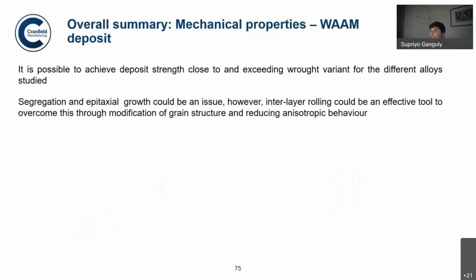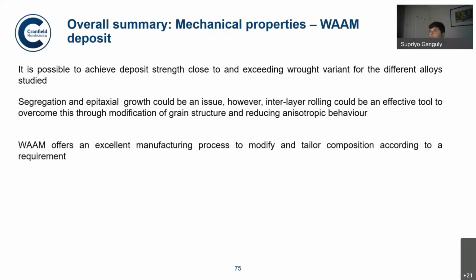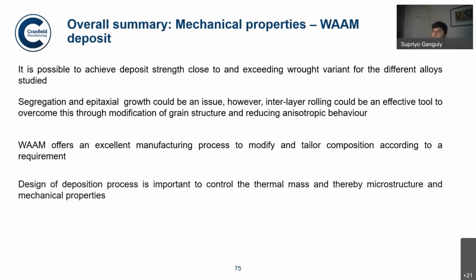Segregation and epitaxial growth in this manufacturing process is an important issue, and interlayer rolling could be an effective tool. So this particular manufacturing technique, WAAM, offers excellent flexibility towards modification and tailoring of compositions. So design of the deposition process is important to address the difference in thermal mass, and this is important because the microstructure and the mechanical properties are inherently linked to the thermal profile of a deposit.